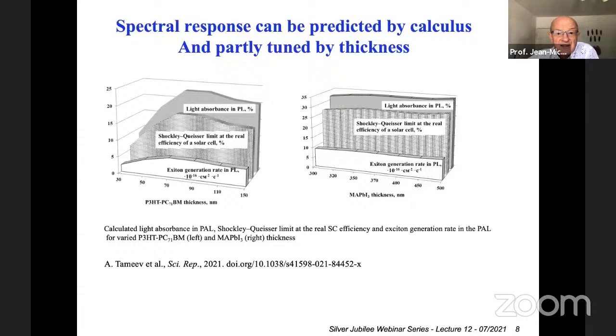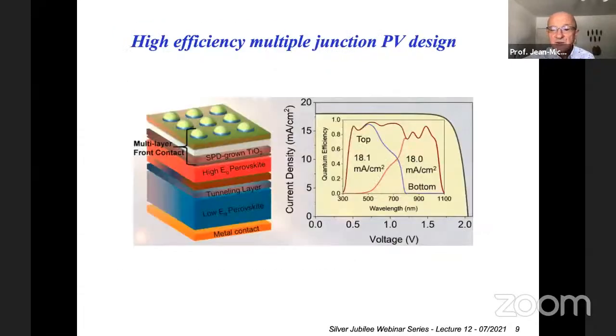And this is an example where we compared some polymer solar cells with methylammonium lead iodide solar cells to check the effect of the thickness. We can robustly, in a controlled way, model the photo response of the devices. And when you can do that, you can also predict what will happen if you stack different layers of perovskites with different band gaps, like in the first device of a photodetector that I was showing.